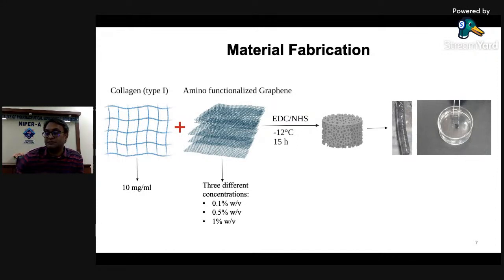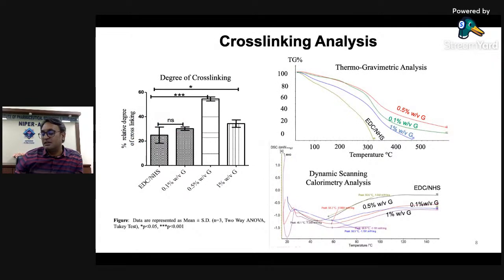So we have used different concentrations of graphene to optimize the whole protocol and then further characterize the material. In the characterization, we first wanted to know how much cross-linking has occurred, so we checked the amine functionalities.